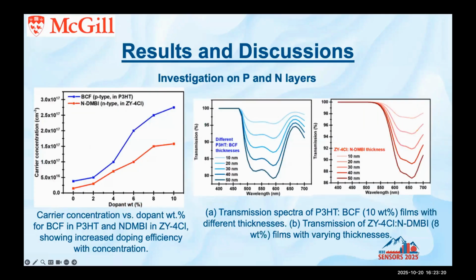First of all, we needed to find out what kind of P and N layers we needed to use in our structure. So what we did was add the dopant materials. We selected N-DMBI for the N-type dopant and BCF as the P dopant. We added different weight amounts of dopants, and technically we expect that at different dopant values, we have different carrier concentrations. We saw that after adding 10% dopants, the carrier concentration starts to plateau, and so we stopped adding more. This was one of the criteria that we looked at.